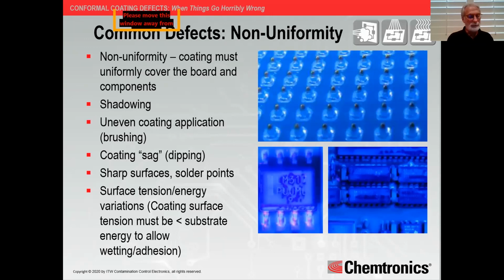Okay, uniformity, or in this case, non-uniformity. The coating, as Kevin mentioned, must uniformly cover that board and all of the components. If it does not, it could be a condition that may be a defect. Now, I'm not sure how many of you know what shadowing is. Shadowing is caused by the geometry of the board, where you have a short component right next to a tall component. And your method of application may prevent that shorter component from being uniformly coated, just because it's being blocked by the taller one. That's what's considered shadowing.